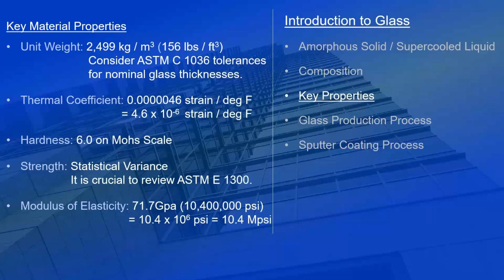The strength, we're going to talk about the strength of glass later on in this presentation. It's an interesting topic. And then of course the modulus of elasticity. Stiffer materials have a higher modulus value, softer materials have a lower modulus value. The modulus of elasticity of glass is approximately 71.7 gigapascals, 10.4 mega psi. The two dominant properties that we look at structurally, though, are the weight and the strength.